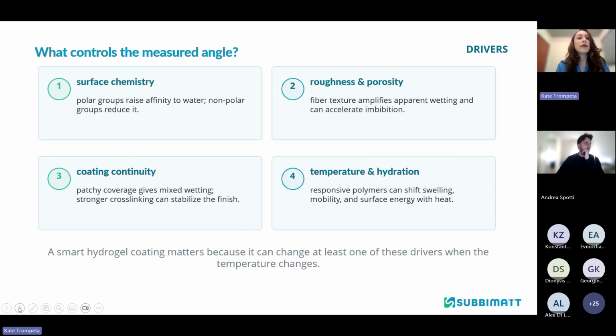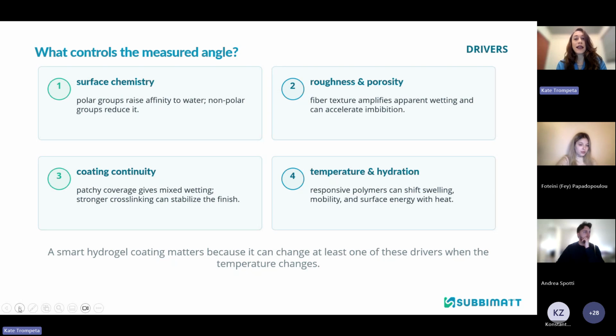So what controls the measured angle? First of all, the surface chemistry. Polar groups raise affinity to water, while non-polar ones reduce it. Then there are the roughness and porosity of the fabric. The fabric texture amplifies apparent wetting and can accelerate imbibition. The coating's continuity is also very important. If we have patchy coverage, this can give mixed wetting. Also, stronger cross-linking can stabilize the finishing.